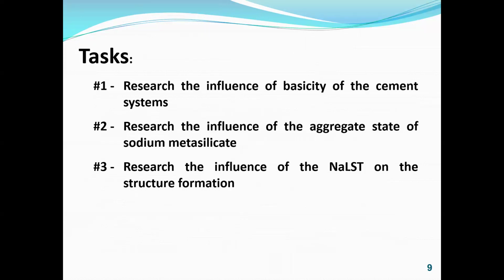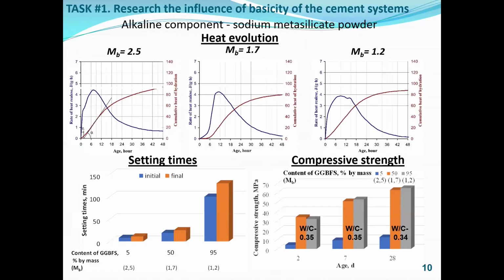The research work was divided into three parts. Task 1. Research the influence of basicity of the cement system. Sodium metasilicate was used in solid form. It was shown that with the decrease in the alkali-activated cement system basicity from modulus of basicity 2.5 down to 1.2, the structure formation processes retarded. An increase in the duration of the induction period, as well as a decrease in the degree of hydration, confirm this fact.